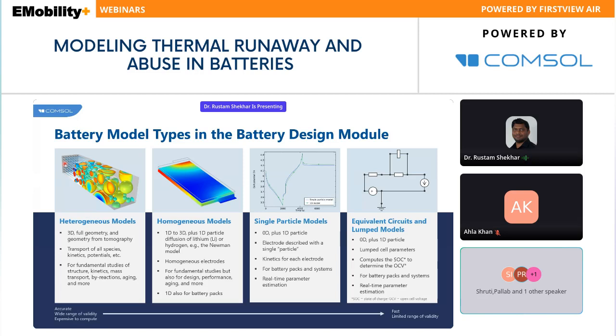In both conditions, the difference in mass transport is there, and then you will see dendrite growth or lithium plating will happen. So if you want to go into that detail, where you want to know how lithium plating is happening, how gas formation is happening, how SEI formation will affect the mass transport, all these detailed scenarios can be modeled in heterogeneous models. There you can identify the abuse conditions and abuse scenarios from the battery system, specifically in one particular electrode, and that can be done for both electrodes. So you will have a single battery where both electrodes, current collectors, membrane and separators are placed, and you can do one detailed analysis.